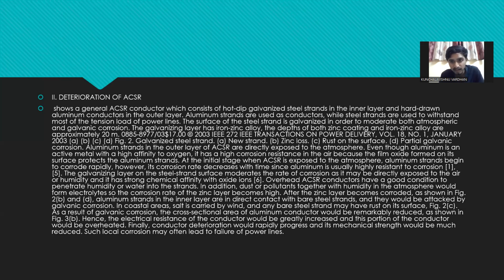Overhead ACSR conductors are in a good condition for humidity or water to penetrate into the strands. In addition, dust or pollutants together with humidity in the atmosphere form electrolytes, so the corrosion rate of the zinc layer becomes high.